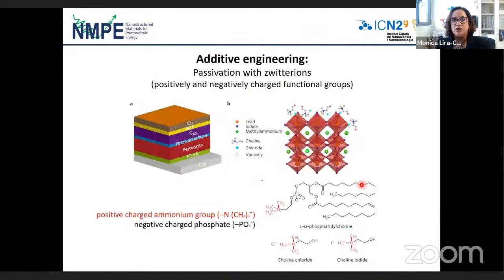So one of the things I want to talk to you about today is additive engineering. There are many methods being used to improve the stability of solar cells. This additive engineering means people are adding these additives on the surface at the interfaces with the transport layer, but also inside the solution when you prepare the halide perovskite. What you want to do is passivate defects, because defects are recombination centers.